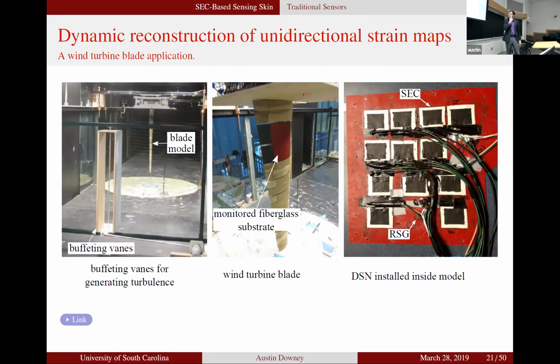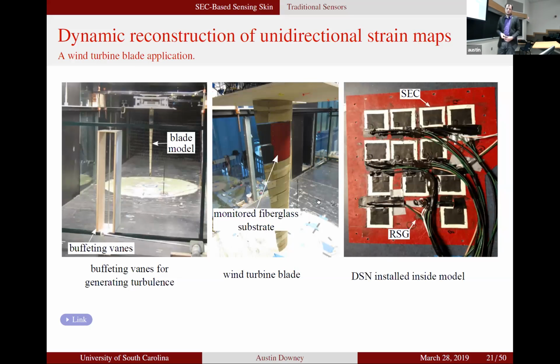So another thing that we can do that other sensors have issues with is full field strain measurements. Of course you could do this with digital image correlation, but that's hard in a monitoring situation. So at Iowa State University, we have a wind tunnel. And what we did is we built a model wind turbine blade, introduced some buffeting to it. We have this fiberglass substrate on the side. And then inside of that, we put 12 SECs. These are much smaller SECs, but they're still the same thing.